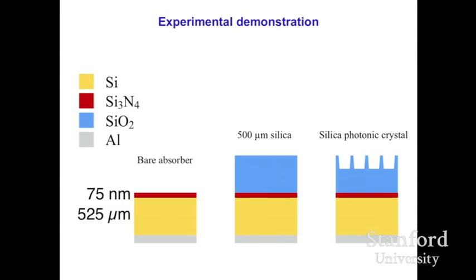So we have done some initial proof of principle demonstration experimentally. And in this experiment, as the baseline, we take a silicon wafer that people routinely use as a starting point for solar cell. So this is the same silicon wafer solar cell with a silicon nitride anti-reflection layer that people put in. And then to cool this down, we compare 2 structures. One of them is a silica structure, a 500 micron thick silica structure. And the other one is a silica photonic structure that we measure where we etch into the silica structure.